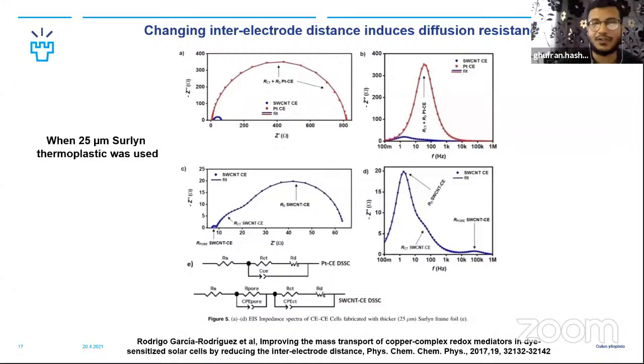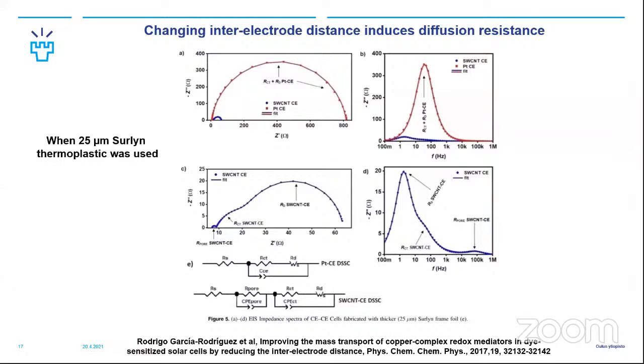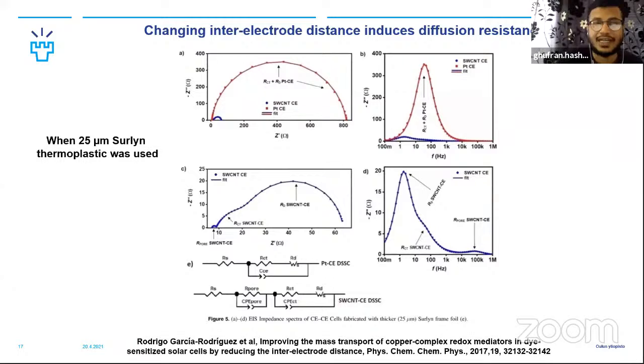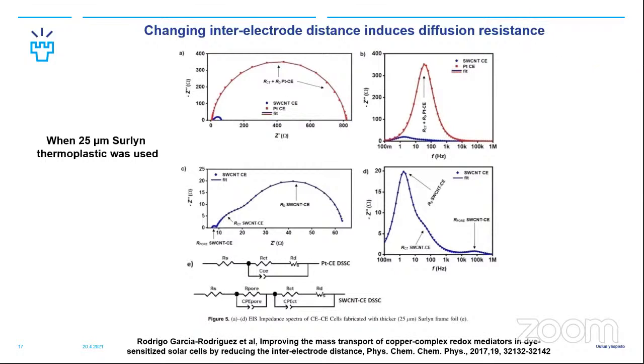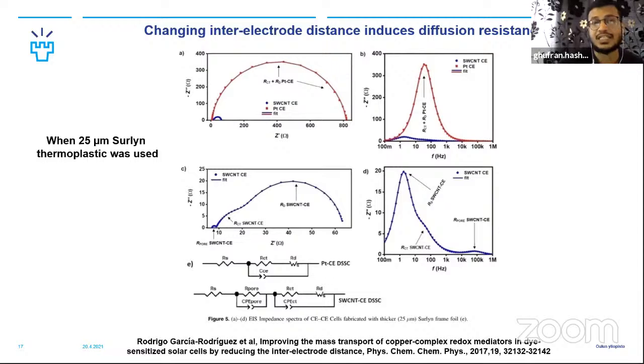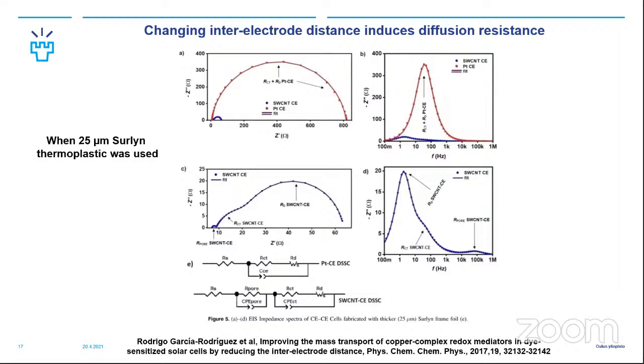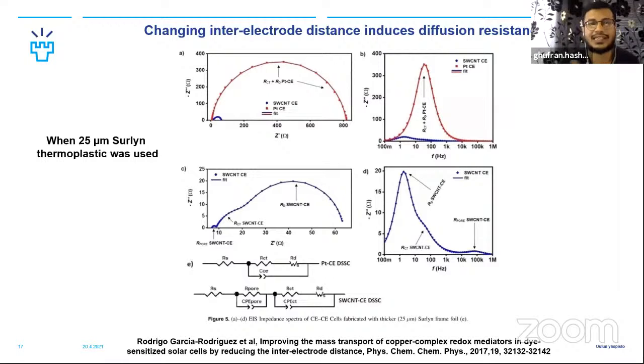But in this carbonaceous material, the first one, as I mentioned, appears as a very small semicircle, so we can't see that profile properly. And the charge transfer resistance for the platinum appears at the high frequency response, but in carbonaceous material it appears at very low frequency response. That's why it is always obligatory to make the symmetrical cell, because mostly in these iodine cells, even this small semicircle, researchers are claiming that this is a charge transfer resistance. No, it's not. It's the diffusion resistance.